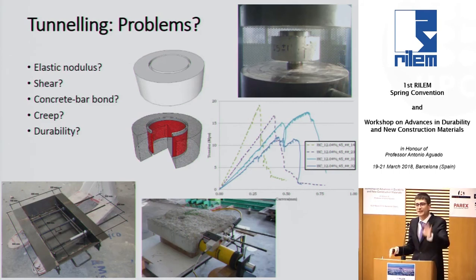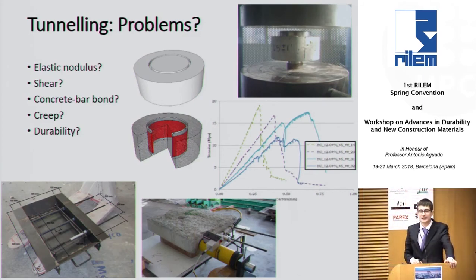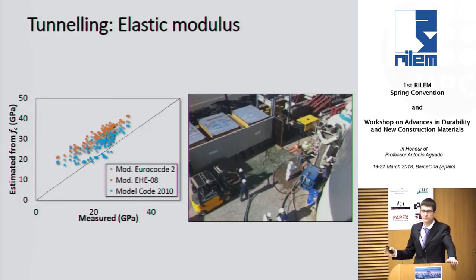So we have sprayed a lot at the lab, and in tunnels also, analyzing different aspects of the mechanical performance of the material. Now I'm going to cover just two of them, the elastic modulus and the durability, to give you a glimpse of what we've found. For the elastic modulus, we have sprayed at the lab, measured the elastic modulus for different mixes, different compositions, and compared with the prediction of elastic modulus using guidelines like Eurocode, the Spanish concrete instruction or Model Code 2010. And what we found is that they don't match, right? So the equations that we have for conventional concrete are not working well for sprayed concrete.